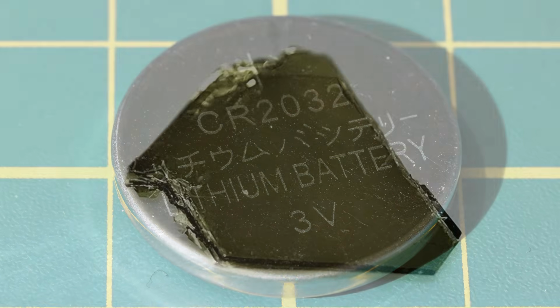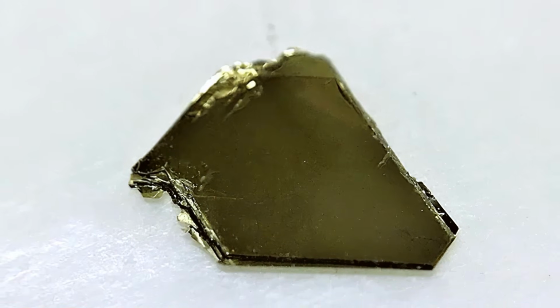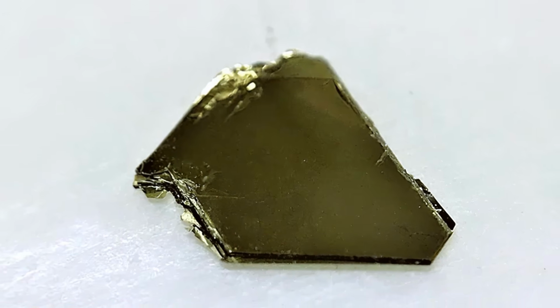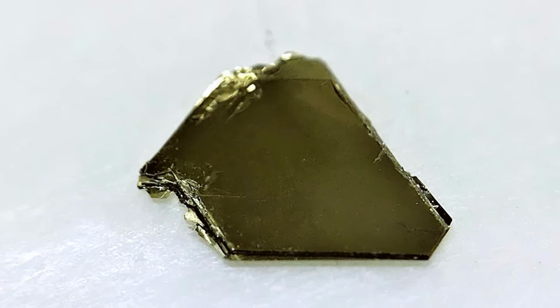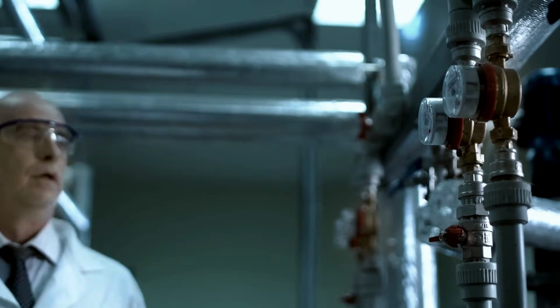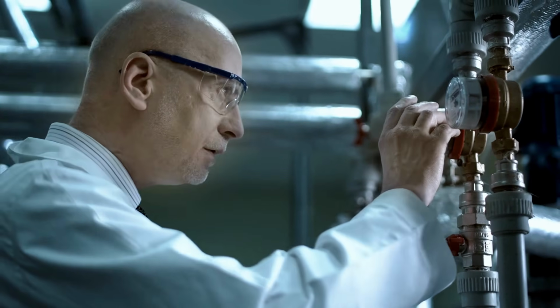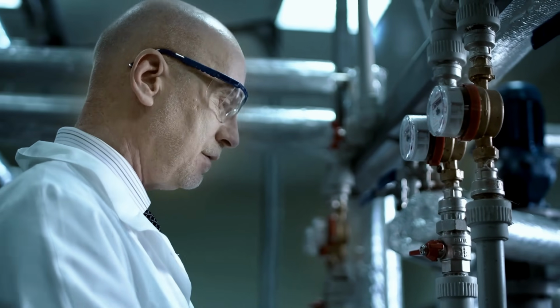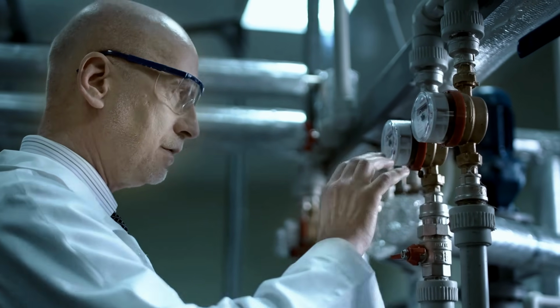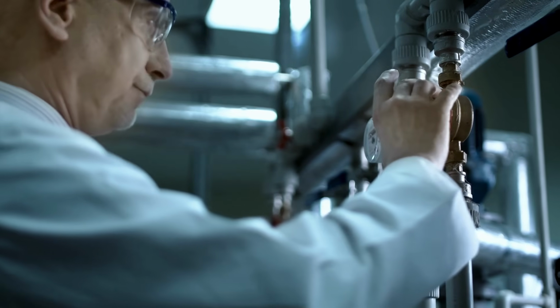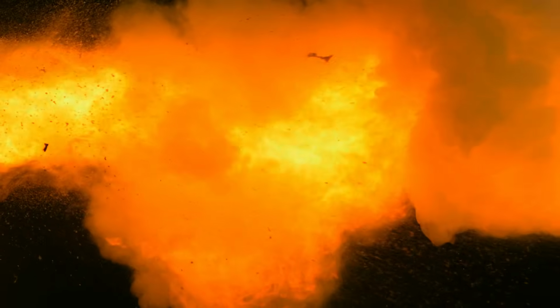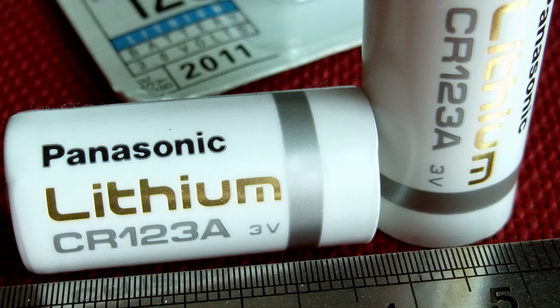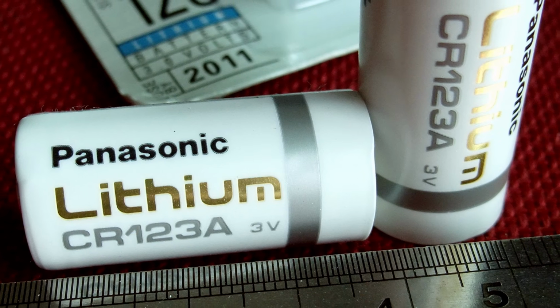Whittingham's initial use of titanium disulfide had proven to be impractical. Its raw form cost over $1,000 per kilogram in the 1970s, and it also required a complex and costly synthesis process. Furthermore, when exposed to air, titanium disulfide reacts to form hydrogen sulfide compounds, which have an unpleasant odor and are toxic to most animals. The experimental cells were also dangerous, as pure lithium will instantly react with water or even moisture in the air, releasing flammable hydrogen gas.